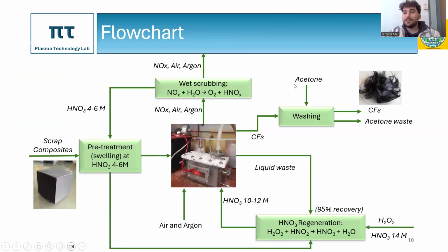Now here is a really simplified flowchart of our process. Initially, the scrap composites are pre-treated in a less concentrated nitric acid solution. Then the plasma-assisted solvolysis takes place with a more concentrated nitric acid solution and with a constant gas flow of air and argon. From there, the carbon fibers are retrieved and washed with acetone, while during the treatment, a small amount of NOx gases are produced, and all the exhaust gases, including air and argon, are led into a wet scrubbing system that we have developed.